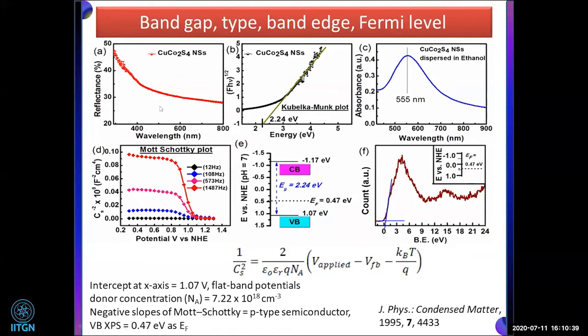Then we conducted the Mott-Schottky plot. From there we found that it is a p-type semiconductor because it has a negative slope, and from the intersection of this point we found the VB of the material is 1.07 electron volt. As the band gap of that material is 2.24, it is not difficult for us to find the CB. And if you can see now, the CB is much lower than the hydrogen evolution potential, it is minus 1.17. So very good for hydrogen evolution reaction, but not good for oxygen evolution reaction.